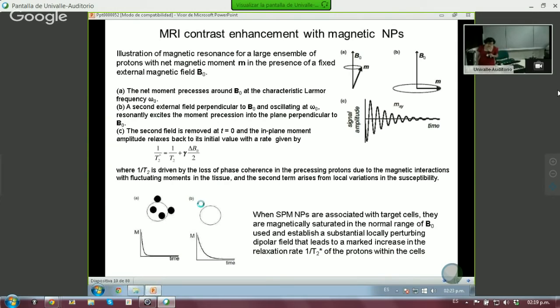And so now we move on to talk a little bit about the MRI contrast enhancement with magnetic nanoparticles. Here, again, I have given the whole physics behind it, but what is very important is that when the superparamagnetic nanoparticles are associated with the target cells, they become magnetically saturated in the normal range of the applied field used. And in a way, we can have a substantial locally perturbed dipolar field, which leads to a marked increase in the relaxation rate 1/T2*.